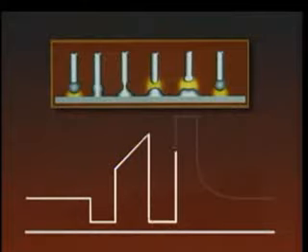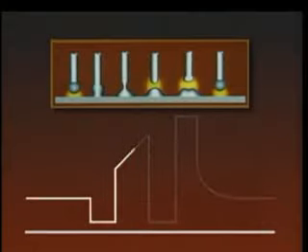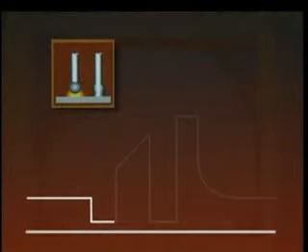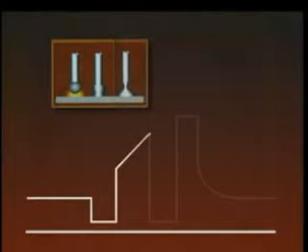Let's break down the waveform for a better understanding of waveform control technology. The STT provides a very specific waveform control that instantaneously reacts to the arc during short circuit welding. At the initial shorting of the electrode, the STT process reduces the current or energy to minimize spatter. Next, a high current is applied, accelerating the molten metal transfer to the weld puddle.